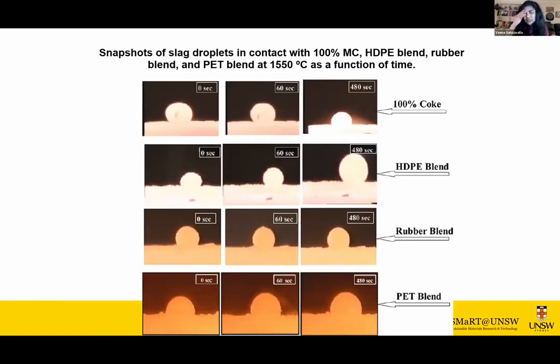So what these kinds of images are showing you is that as we capture these in-situ transformations and how the chemistry evolves under different conditions inside these types of steelmaking operations, compared to the very first row where there's 100% coke being used, as opposed to a lot of these other polymeric materials, we actually get far more efficient reactions. And these slag forming reactions have in fact shown that the overall steelmaking efficiency is enhanced significantly.